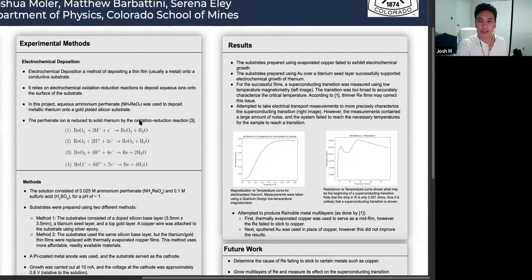We tried preparing substrates a few different ways. The first way was thermally evaporating copper onto the substrate. The reason we wanted to do this is because it's much cheaper than the mainstream method, which is titanium and gold seed layers. Unfortunately, we couldn't get that to stick well to our silicon substrates. And when we tried growing rhenium on that, the copper just dissolved.